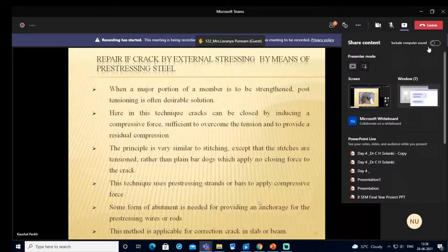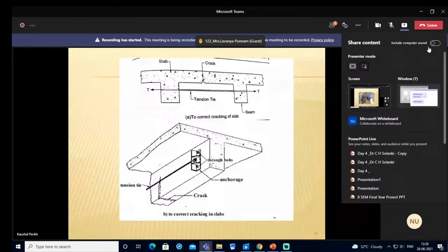So here the principle is very similar to stitching, except that the stitches are tensioned rather than plain bar dowels, which apply no closing force to the crack. Here this technique uses prestressing strands or bars to apply compressive force. Some form of abutment is also needed for providing an anchorage for the prestressing wires or rods, as shown in this image. In this first figure you can visualize that if we have a crack and we apply this tension tie over here, that will create the compressive force to close the crack. See another image for the same approach, the actual image which has been shown over here.